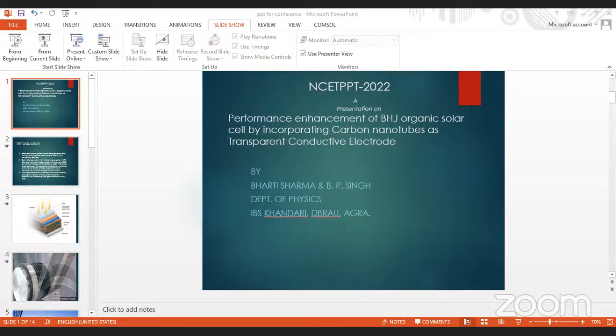In these organic solar cells, we are using TCE, a transparent conductive electrode, which is the major component of these solar cells. ITO is the most popular and widely used commercial TCE nowadays, but there are some drawbacks. It is brittle in nature, and sometimes it is found to have cracks, which degrade the device. So we need alternatives to ITO, and here we are using carbon nanotube to replace ITO.